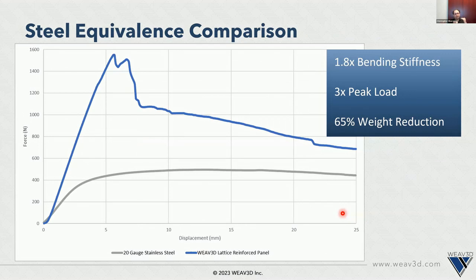But we weren't really satisfied with just doing that benchmark against the organosheet. So we also took that same design and modified it slightly, where instead of using a pure polypropylene material for that middle, we actually used a natural fiber nonwoven mat. The total thickness of this panel was about 2.1 millimeters. By comparison, the one that I showed on the previous slide for the actual belt line was about 2 millimeters. But what we were able to demonstrate is that this same lattice reinforcement pattern, compared to something like 20 gauge stainless steel, was 1.8 times stiffer, 3 times higher bending load capacity, and 65% lighter.